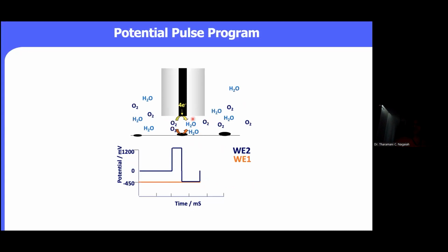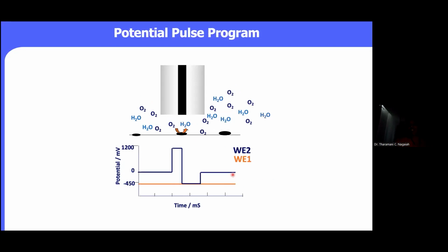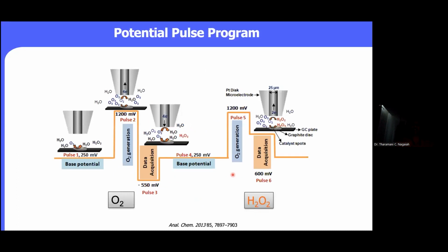So therefore, the amount of oxygen left at the tip will be less. And again, we are applying the base potential where there is no reaction. This kind of potential pulse we keep applying at every grid point. So that means when we move the sample, let's say 10 micrometers, 25 micrometers, we keep applying. So therefore, the spatial resolution of the activity is quite high compared to the macroelectrochemistry. This is one of the extended profile programs.